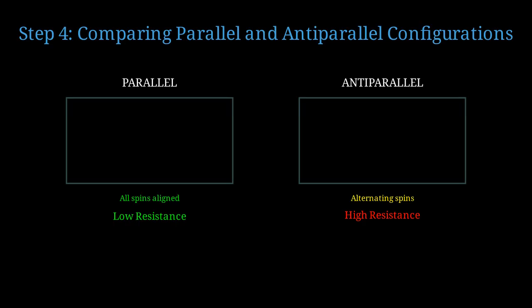Step 4 is systematically comparing the resistance in parallel versus antiparallel magnetic configurations. This is where we see the GMR effect most clearly. Here's the key insight. On the left, we have the parallel configuration, where all magnetic moments point in the same direction, achieved by applying a strong external field. On the right, the antiparallel configuration, where adjacent layers have opposite magnetization, which occurs at zero field in certain structures. The resistance differs by a huge factor between these two states.